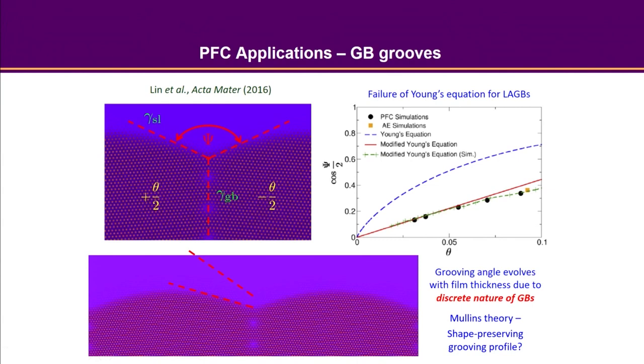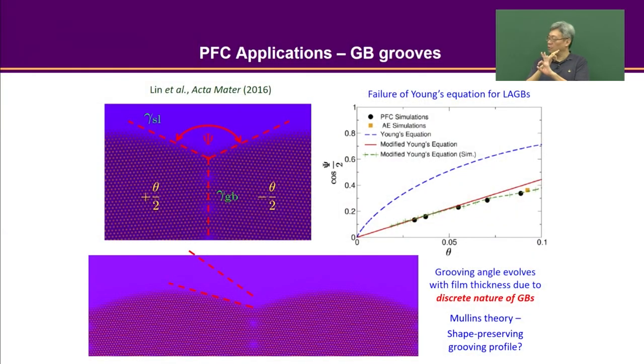But if you just rotate the system by 90 degrees and do the plus minus 2.5 rotating, now you are changing the dislocation structure, so you start to see a pair of dislocations overlapping. Because if I do a 90 degree rotation, the allowed Burgers vector cannot be the one that's horizontal, because you will only have a Burgers vector along a certain lattice plane. So you will only have either the plus 3 degree or minus 3 degree Burgers vector. So in order to have a local average Burgers vector that's perpendicular to a grain boundary, you start to see a pairing of these dislocations.